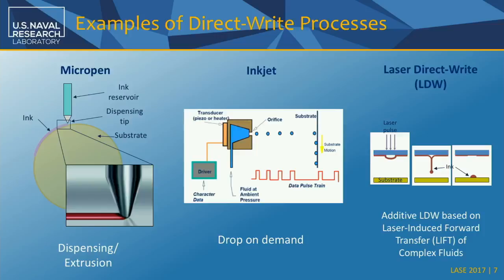We can make a paste of anything we want, or a fluid of anything that we can mix. And sometimes we feel like we're painting: we just take powders and mix them in a fluid, and then we try to make something that looks uniform, spread it on a donor substrate, and transfer it with a laser. And this mechanism here, I'm going to go into more detail, shows how the ejection works: there's a jet that gets formed for low viscosity inks, and that leads to a drop. That droplet is what we collect and form. As we repeat it, we form patterns. We call this droplet our voxel of material. That's our single unit of printing, and we can actually vary that.